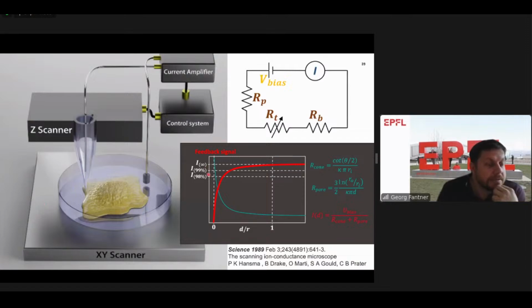This is the same concept, but it's slightly better rendered. So what we have is we replace the AFM cantilever with a glass nanopipette. This is just a quartz physiology pipette pulled to a point to have a very, very small opening. And we put an electrode inside at a very conventional electrophysiology setup. Now, if we are far away with our pipette from the surface, we have the surface here, our cells in an electrolyte solution, in this case, it's just growth medium, and we have the electrode inside the pipette. We have a current amplifier and a counter electrode.